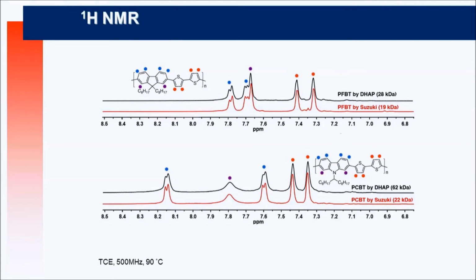So you have to have a time control of the polymerization to achieve a well-defined processable polymer. NMR is, I would say, the right tool to compare. So this is the NMR spectrum obtained from the Suzuki coupled polyfluorene, and what you get from direct heteroarylation polymerization: comparable, totally comparable. The same for the carbazole here, you get more or less the same material. So it's possible to get comparable materials with direct arylation or Suzuki coupling.